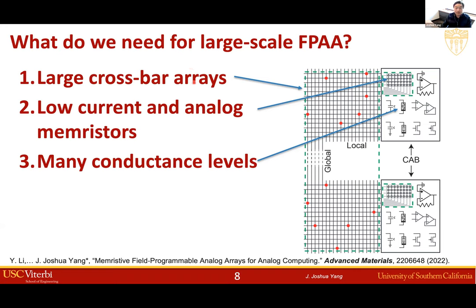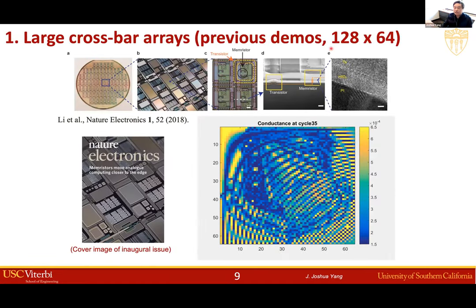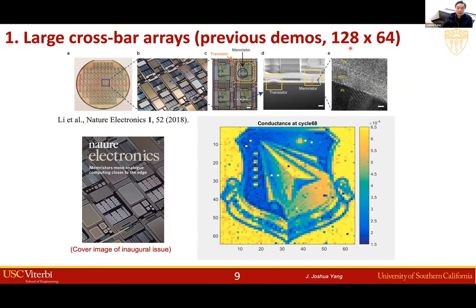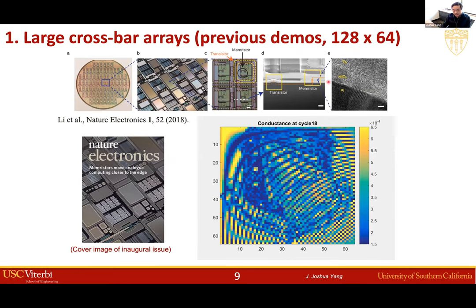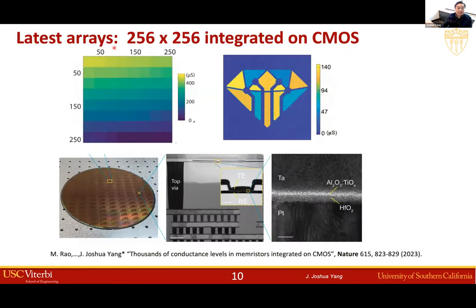First, large crossbar array. This is the crossbar array we demonstrated 5 years ago. Here we demonstrated a 128 by 64 array. And the CMOS part was made, of course, in the foundry, but the memristor was integrated in the university lab. And this shows the latest progress. In this case, we made the array size about 8 times larger, up to 256 by 256, and fully integrated on CMOS, meaning both the CMOS front end and the memristor back end were done in the standard foundry.